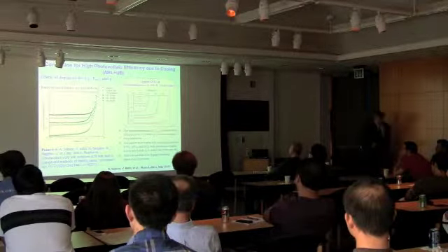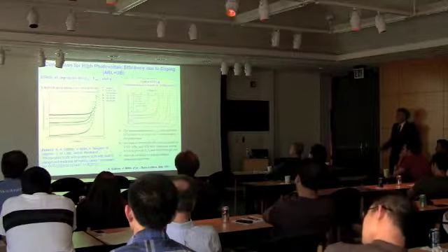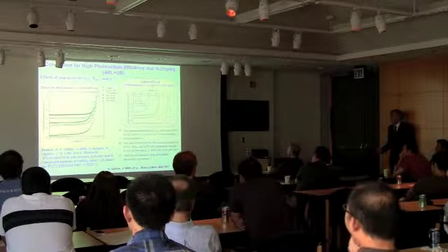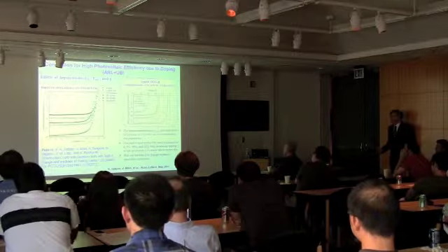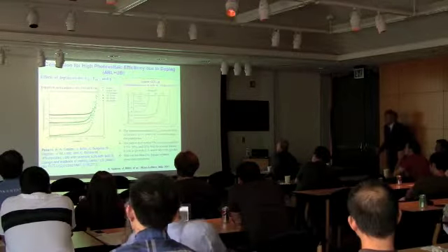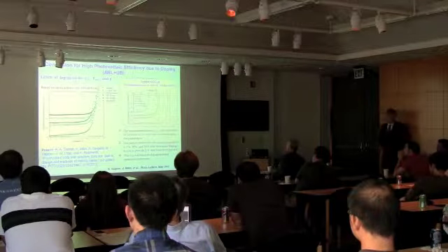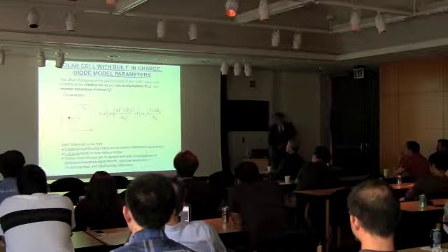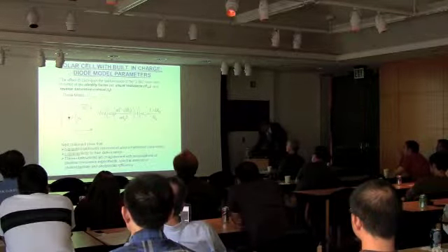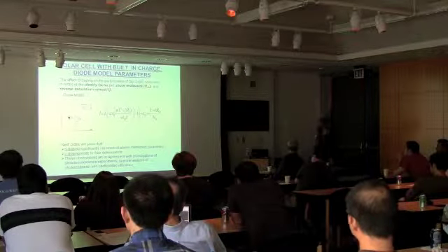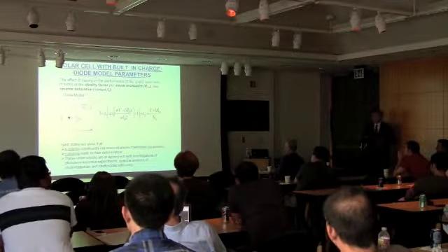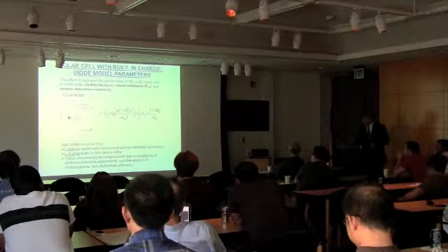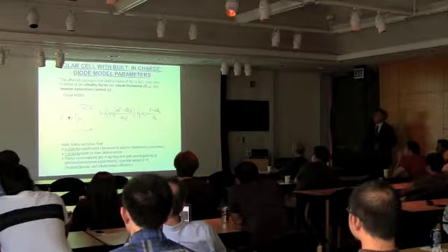it really increases the efficiency, as we show here, in contrast to the previous results of other authors, the overwhelming majority, where they create the intermediate band and then put in more dots. Really what is going on is that you have deterioration of performance in spite of the fact that you have additional absorption. So as it looks like I have 1 more minute to complete, I will show you that we also prove that the quality of the material improves from the point of view of this conventional so-called diode model parameter.